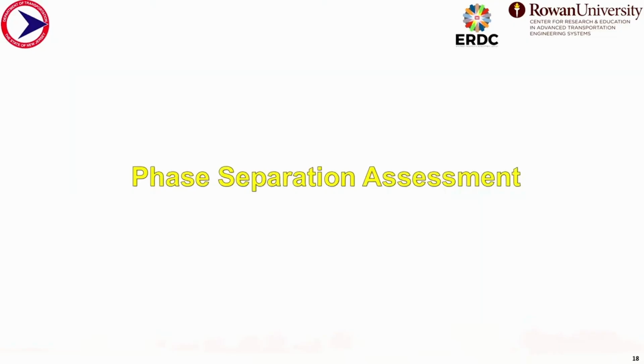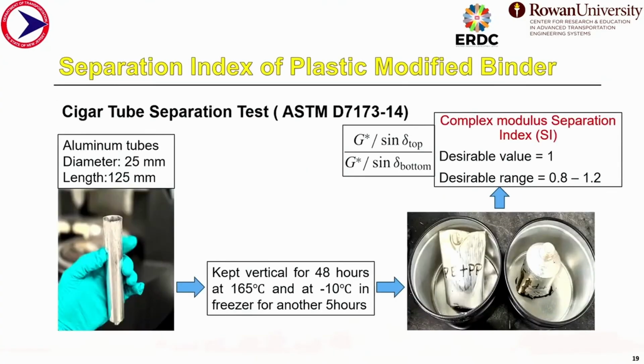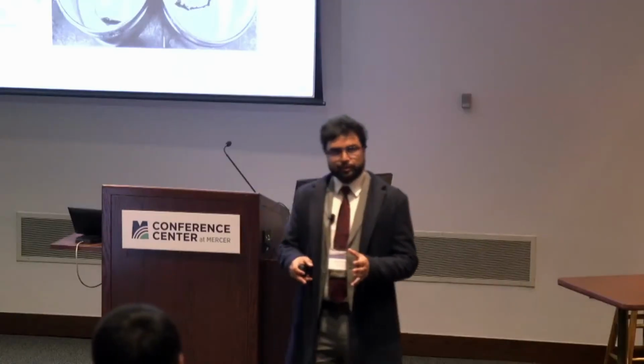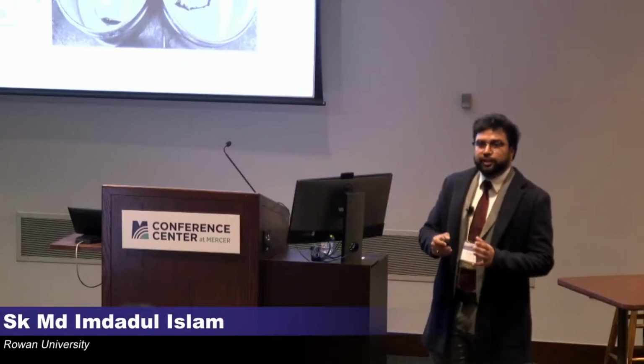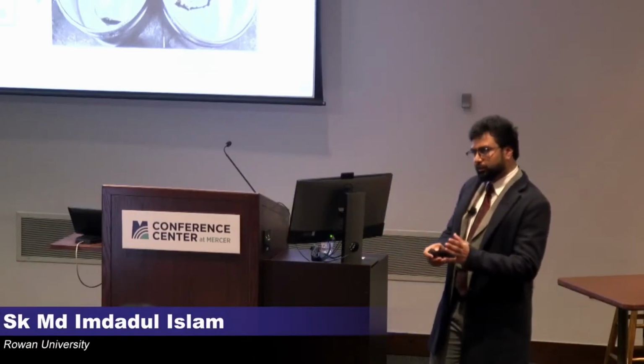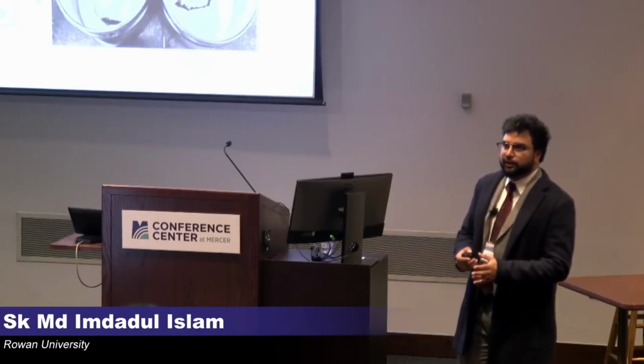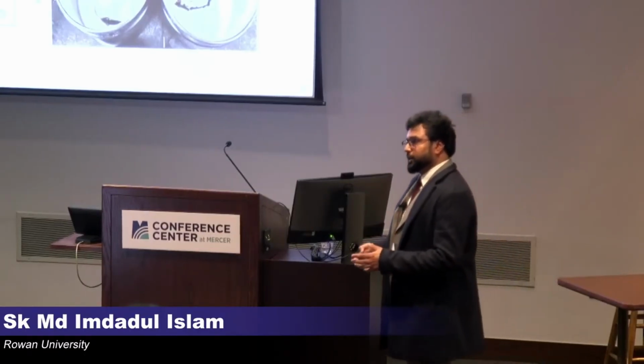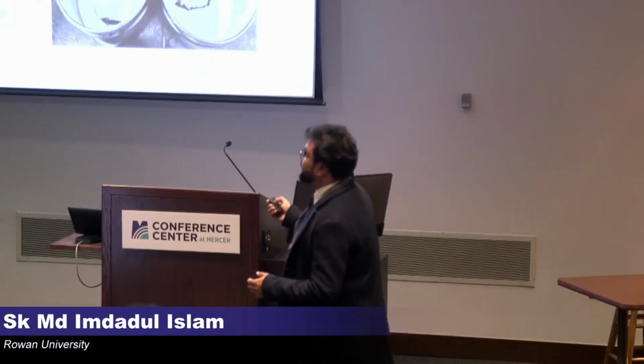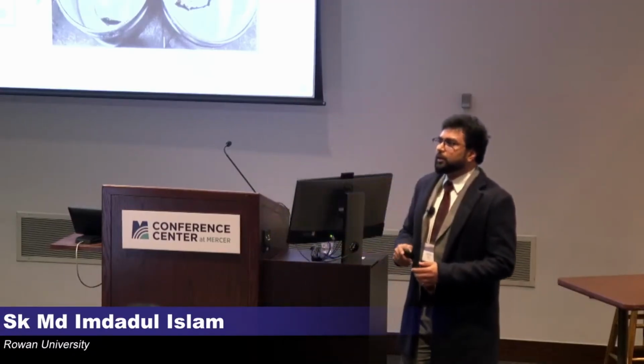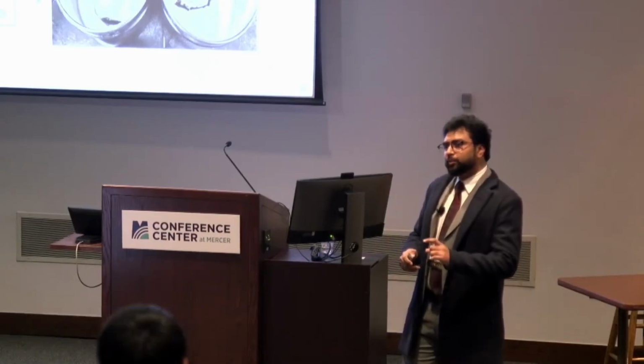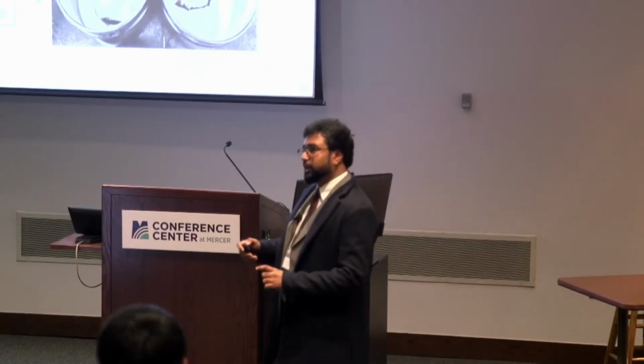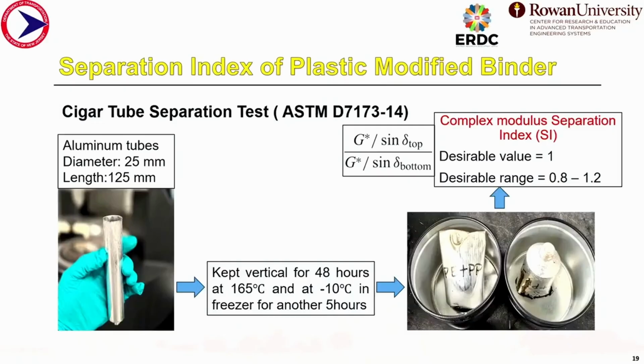Then, after doing all these blendings and incorporating the waste plastics, we are going to the second part of the presentation, which is the phase separation assessment. For this, we did the cigar tube separation test according to ASTM D7173. Here, after blending all these plastic modified binders, we poured them into an aluminum tube, and then we kept it vertically for almost 48 hours at 165 degrees Celsius, and then we shifted it to minus 10 degrees Celsius for another 5 hours. And following that, we discarded the middle portion of the tube, and we kept the top and bottom portion of that aluminum tube, and we ran the DSR analysis to get the G star and sine delta.